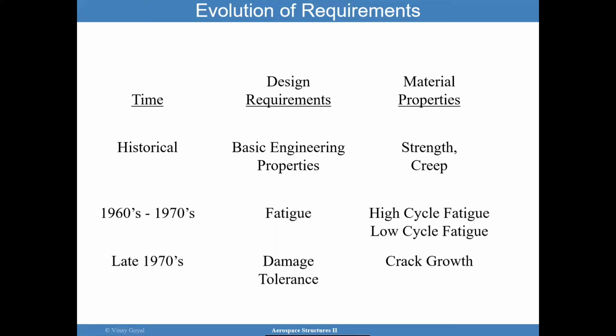But it's important to understand that fatigue and fracture, while somewhat related, are different design drivers. For example, for fatigue, what I'm looking for is that initiation. Once the crack initiates, perhaps I can then switch into damage tolerance. But when I look at damage tolerance, I am assuming that there's some inherent defect that needs to be considered in the design. And if there's no initial defect, then perhaps the fatigue initiation from high cycle or low cycle causes the initial flaw, and then we analyze the damage tolerance.